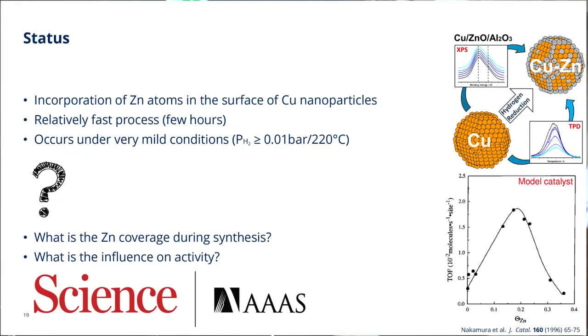So this brings me to a small status before I continue. I've shown you so far that it's possible to incorporate zinc atoms into the surface of the copper particles. It's actually a relatively fast process. This happens just within hours, and it starts occurring already at quite mild conditions. So this, of course, brings up some new exciting questions.